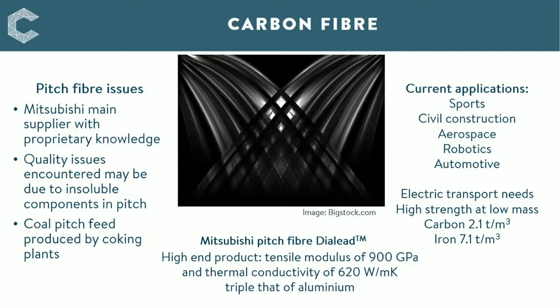Propene is a product of steam cracking of petroleum, and that undergoes some oxidation to form acrylonitrile, which is then polymerized, and that material then provides a wet dope of PAN for the carbon fibre process, which is essentially carbonization of long-chain polymers. And the advantage of using PAN, as I said, is the tight specification from a single feed material. Now, where PAN is a wet spinning process, the use of pitch is a melt spinning process, and I give more details on that in the report.